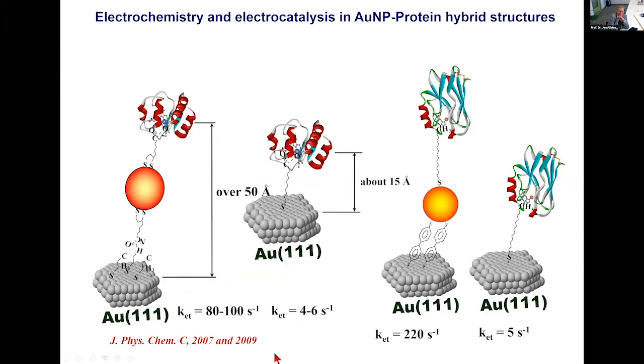And quite amazingly, if you insert a 3 nanometer nanoparticle between a redox metalloprotein such as cytochrome C or azurin, you increase the electron transfer distance by several nanometers. If this had been normal molecular material, then the electron transfer channel would completely be blocked. But instead, when it is a nanoparticle, you can see that the rate constant increases by at least an order of magnitude. And that is a puzzle.